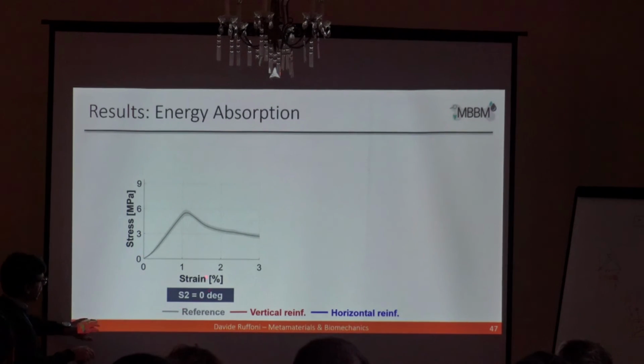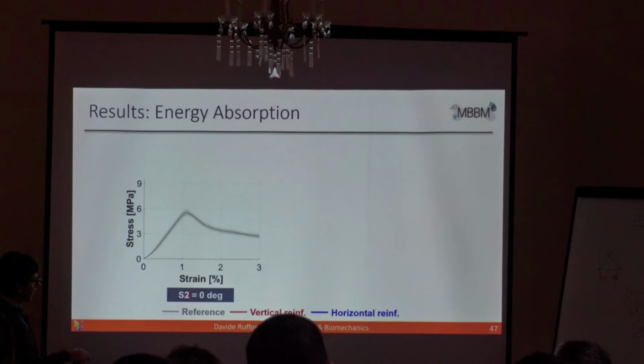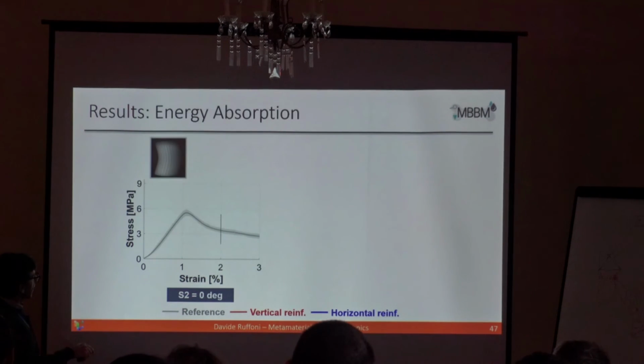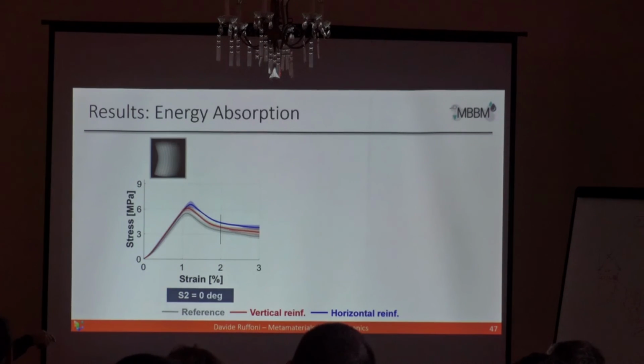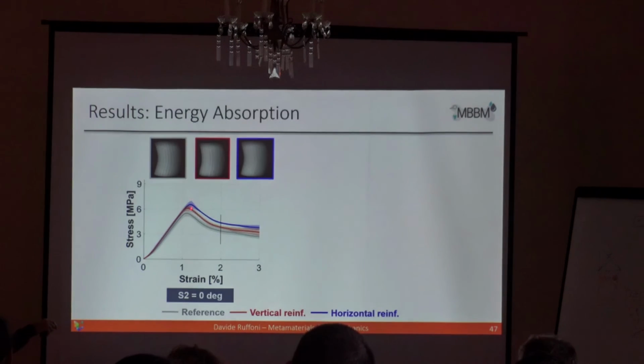So this is how the system fails when the main fibers are oriented vertically. This is a typical buckling failure that you would recognize here. And what is happening when we add vertical reinforcement or horizontal reinforcement? Well, things do not change so much. The system is still failing by buckling. It gets a little bit higher peak stresses, but the same failure strain is observed.